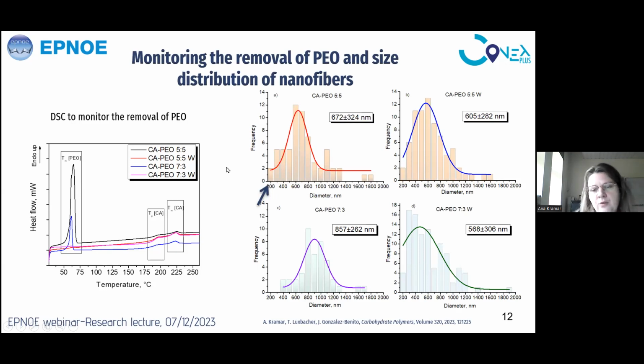When we were studying the size distribution of diameters of nanofibers, we came to a surprising conclusion. As you will recall, in the beginning I told you that pure polyethylene oxide nanofibers have a low diameter, around 200 nanometers. So if we process cellulose acetate and polyethylene oxide nanofibers at the same time, but they are formed separately, this component in the distribution would be removed after washing. But it was quite the opposite. We in fact obtained a size distribution curve much more shifted to the right. It happened whether we were using a 1:1 ratio of polymer or more cellulose acetate than PEO.